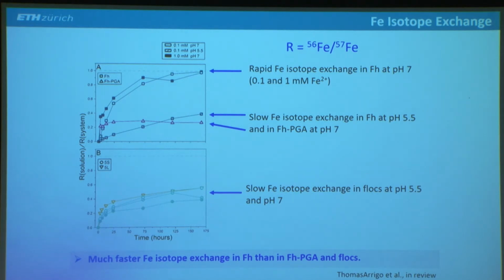If we do the same experiment with the ferrihydrite polygalacturonic acid at pH 7, we see a rapid reaction initially, but then it's completely leveling off. So it seems like it really stops reacting. So there might be some part of the iron protected. And with the flocks, we also see a rapid initial reaction and then a very slow reaction, but it's never as fast as with pure ferrihydrite. So again, it seems like the organic matter has a big influence on not only the recrystallization, but also on this atom exchange process. We don't really understand fully why this is the case.